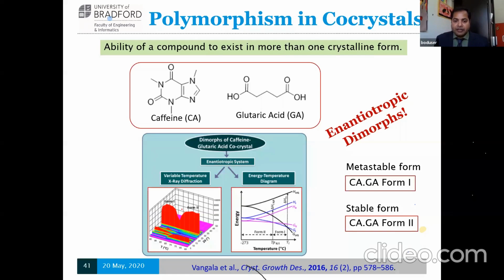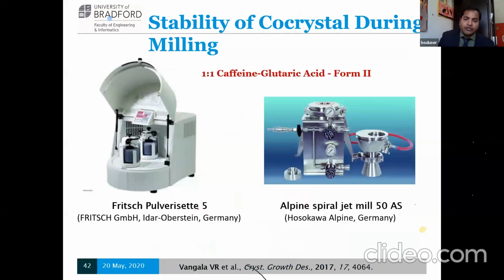I'm not going into the details of this particular work, but we thoroughly carried out thermodynamic investigations, and we understood the relationship between these two polymorphs, which are enantiotropic dimorphs. With that idea in mind, we have taken the stable form, which is caffeine glutaric acid form 2. This is our starting material. We have used a solution bulk scale process. One of our colleagues, Yushan, prepared 500 grams, 1 kg of material via solution crystallization. We use this form 2, the stable form, and subjected it to two of the very commonly used milling processes. One is a planetary ball mill, another one is a jet mill.